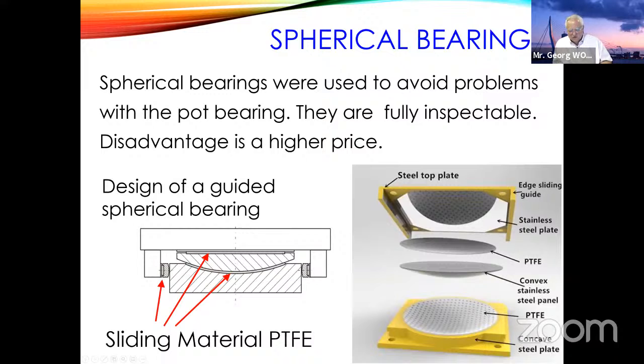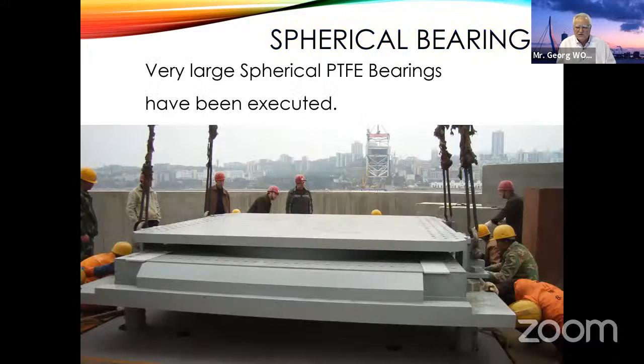Okay, then to avoid the problem with the pot sealing, in a lot of countries they changed to spherical bearings with the PTFE because at least you can check the PTFE from outside. And it was working quite okay, but this type of bearing was more costly than the pot bearing, about, I would say, 25%. But very large such spherical bearings have been installed. You see a picture here.